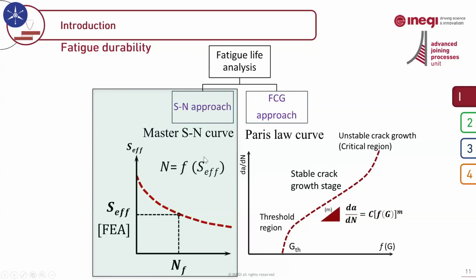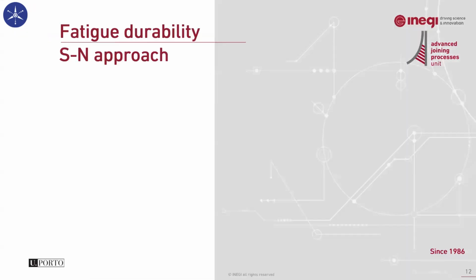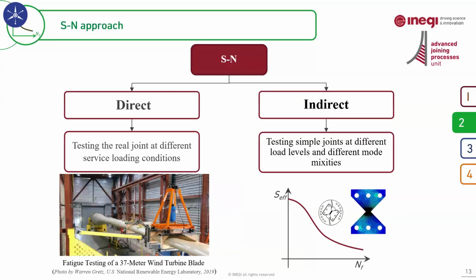Now I'm going to start with SN, and I will share with you some results based on the SN approach, and then I will continue with the fatigue crack growth approach. The SN approach can be implemented in two ways, direct and indirect. In the direct method, you test the real joint to obtain the fatigue life directly from the test and without any specific post-processing. In such cases, usually you need to test a full-scale structure.